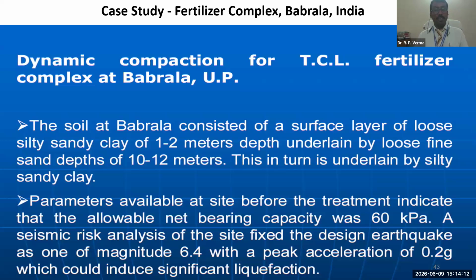Our final case study focuses on the TCL fertilizer complex in Babrala, Uttar Pradesh. The site profile consisted of highly liquefiable loose fine sand extending down 10 to 12 meters, with a very low initial allowable net bearing capacity of just 60 kilopascal. A seismic risk assessment indicates that a magnitude 6.4 earthquake with a peak acceleration of 0.2 g would induce severe liquefaction across the site.